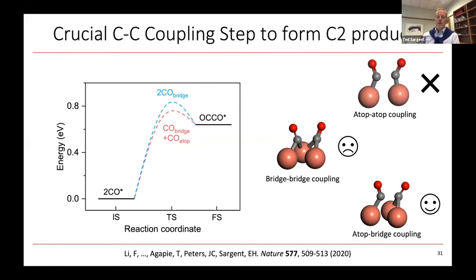And so in conversation with Teo and Jonas and their colleagues, we started with a recognition that from computational studies, the barrier to the desired coupling process where you take two adsorbed carbon monoxide intermediates and you do the CC dimerization to produce the C2 product, such as ethylene that we were working on in this case, is influenced by the binding motif of the CO intermediates. And if you had two bridge-bound or two atop-bound CO intermediates adsorbed on your copper catalyst, then in one case you had just an unstable, this was an improbable thing to occur. And the other case you had a higher barrier to the coupling reaction, but if you could reach a point where you had managed the ratio of these two binding motifs on the copper to be approximately 50-50, it looked to us like you could lower the barrier to the coupling reaction.